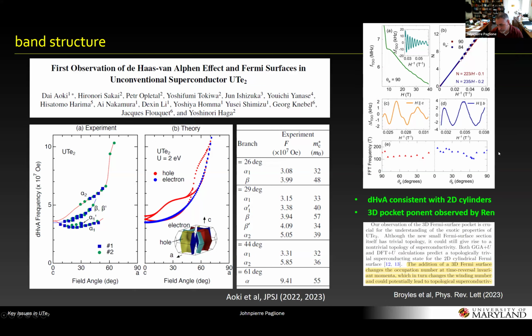Of course, there's been some more recent developments, in particular, the ability to measure quantum oscillations, first seen by the Aoki group in the salt flux crystals, and by a few other groups now, of course. And the really interesting thing to me is that the observed frequencies more or less match the calculated band structure. There's some quibbles about what fits and what doesn't fit here, which is the band structure of light electrons, but nevertheless, there's a very heavy mass observed through the Lifshitz-Kosevich analysis. And so there's been lots of discussion about how we understand the F weight in this band structure, and whether there's a need for another additional piece of Fermi surface that's not observed, for instance.